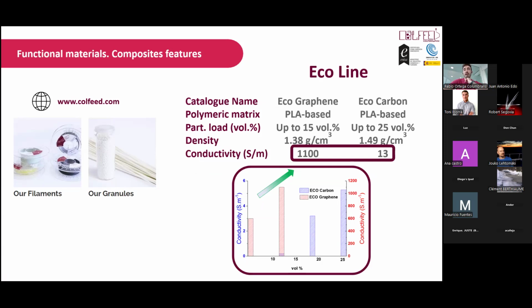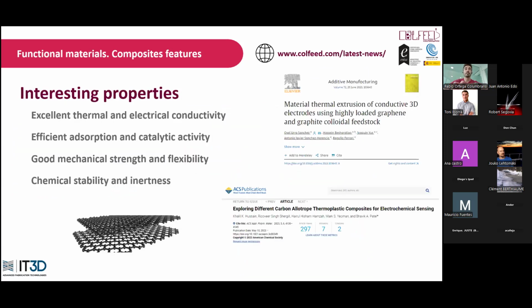I would like to point out how the material with 15% in volume of graphene and the rest of PLA reaches electrical conductivities in the same order of magnitude as the shielded prints, just in the filament. So the printed parts should be higher.